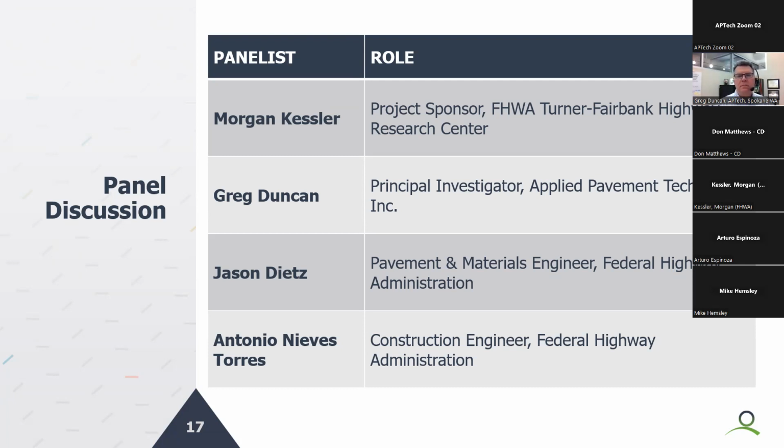And that's where looking at your pen and viscosity and developing the relationship based on the area of the country helps you be mindful of, number one, the asphalt content, the virgin asphalt that you're putting into the mix, and then your overall asphalt content, and then also your gradation that you're trying to use. So thankfully we were given that luxury that we could move to a Type 3 in that instance. But those are the kind of things you have to be on the lookout for during the design of materials using RAP in pavement preservation. So did that pretty much cover what you wanted me to, Greg?